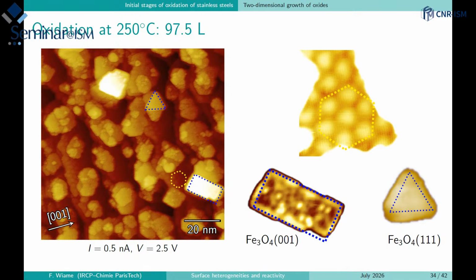And so if we are now going up to a larger value of 100 Langmuir, then we have the surface which is fully covered with the chromium oxide, but we still have some iron oxide which is growing on top with different orientation. With some orientation, for example, Fe3O4, the 001 surface is growing much faster than the 111 orientation. So you can see in the STM image that the island is much higher, it's a much brighter island. So this orientation is growing faster on the surface. So not all the orientations of iron, there are several orientations, are growing at the same pace.